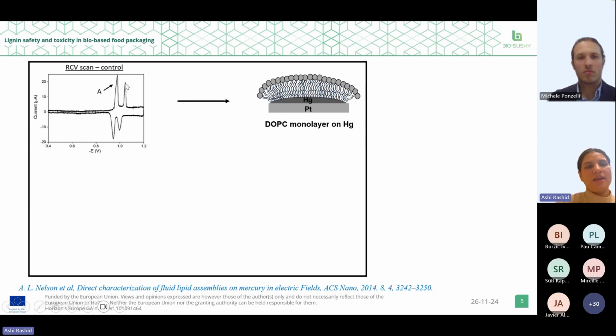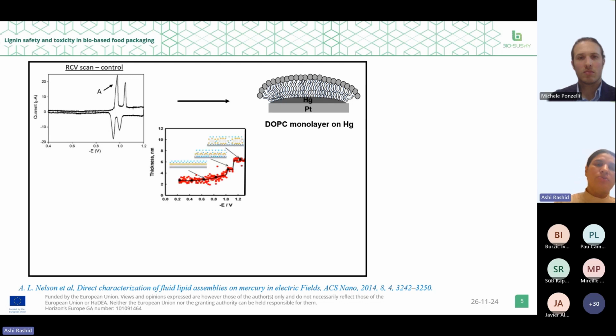These regions have been investigated in detail and are reported to be associated with the underlying phase transitions. For example, in the constant current region, the lipid layer is impervious and very well packed. The first current peak corresponds to the electrolyte penetration, followed by the second current peak, which indicates the reorientation of lipid molecules, resulting in the formation of a lipid bilayer in equilibrium with the electrolyte.